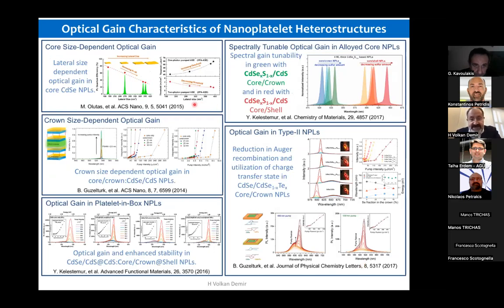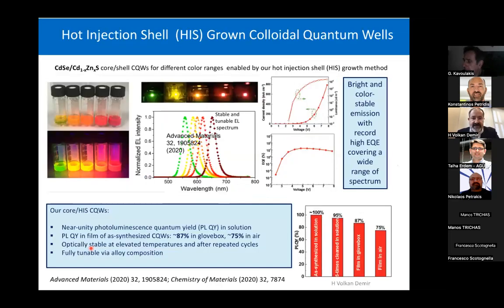I won't go into the details of this. This can be looked into further if anyone is interested, but studying core size dependent optical gain, crown size dependent optical gain, and spectral tuning behavior, type 1 versus type 2 based optical gain, and particularly this, again, platelet in a box architecture, which is the most promising as expected. In this type of architecture, as we found out, it turns out that hot injection shell growth is very critical. This is a very well-known technique for colloidal quantum dots. But at the time, we didn't have a solution for this type of hot injection-based shell growth.